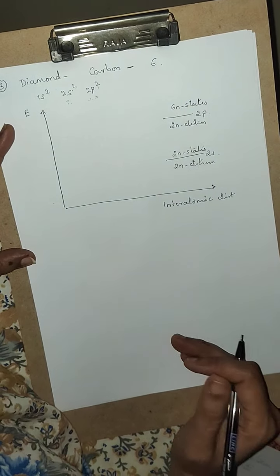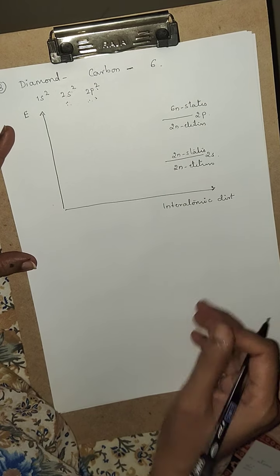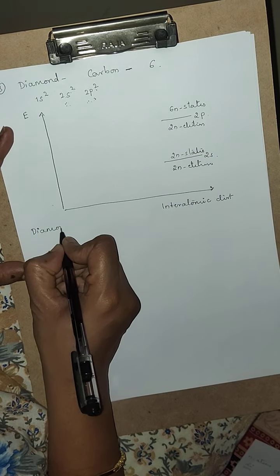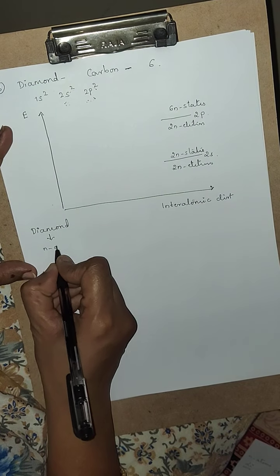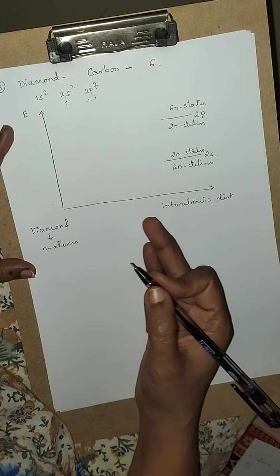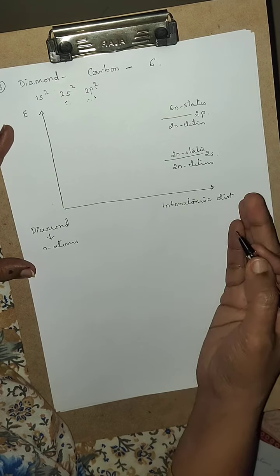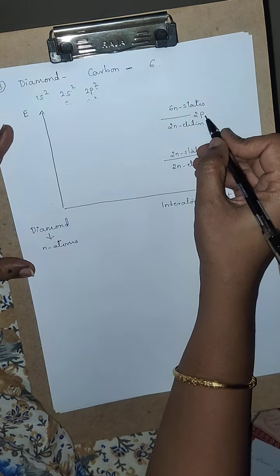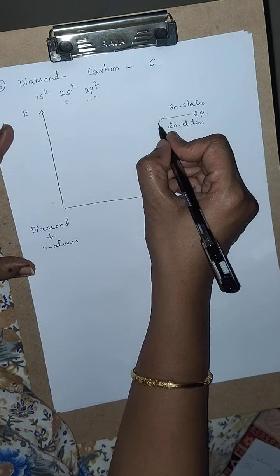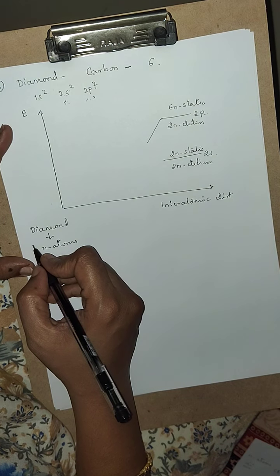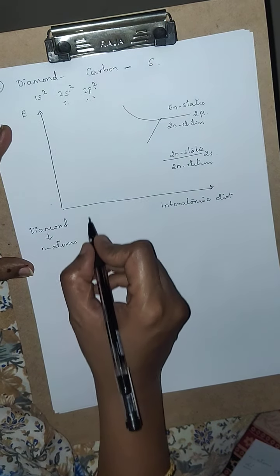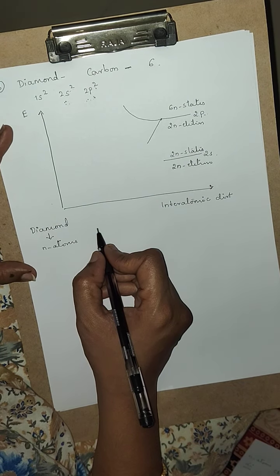What we understood in the previous discussion about silicon and lithium applies here too, for diamond, which has n number of atoms. All the atoms start interacting with each other. As you go on reducing the interatomic distance, first the 2p level is going to split, such that some of the electrons out of these 2n will reduce their energy, and the levels will start shifting downwards, and some of the electrons will increase their energy, and the energy levels will start moving upward.